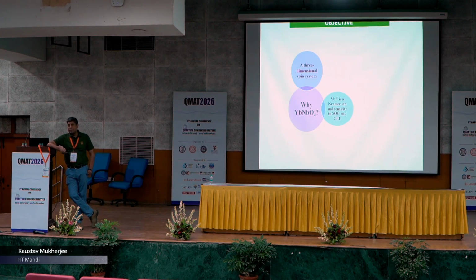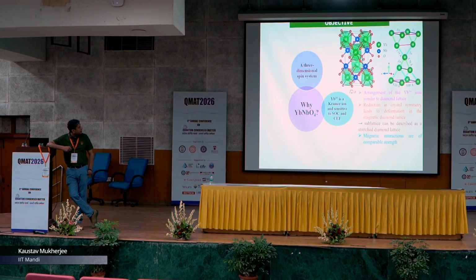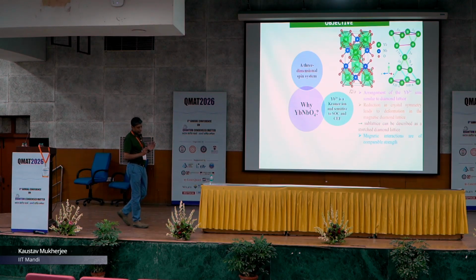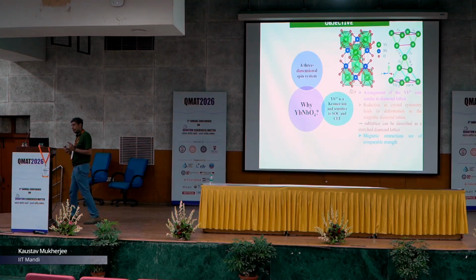Using the lattice parameters obtained from the Rietveld refinement and the VESTA software, we made this structure of YbNbO4. Here the Yb ions are the green ions and are surrounded by 8 oxygen ions having 4 different bond lengths. Also the Nb ions are surrounded by 6 oxygen atoms having 3 different bond lengths. So basically this structure has distorted YbO8 and NbO6 polyhedra. And also in this structure, the arrangement of the Yb ions, which are the magnetic ions, is similar to that of a diamond lattice. However, this system is in a monoclinic symmetry.